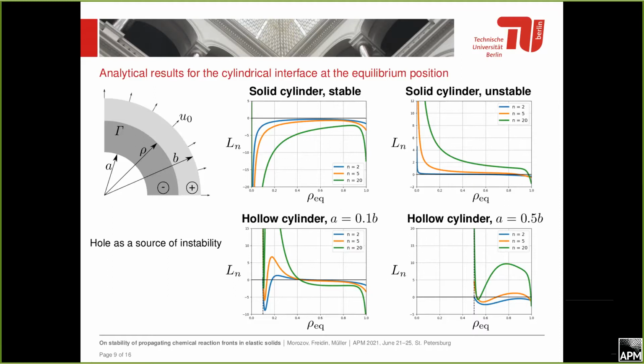Also, these plots are for solid cylinders, and we started with a hollow cylinder problem, and we see that the hole inside the cylinder introduces some instability in the area close to the hole. So if we consider even a hole of 0.1 of the external radius, we see that if the equilibrium position were 0.2, it would be unstable, even though the material parameters we are looking at are considered stable. If we introduce a bigger inner diameter, we see that for a configuration that is stable in terms of material parameters, these interfaces will be unstable, just due to the internal hole.